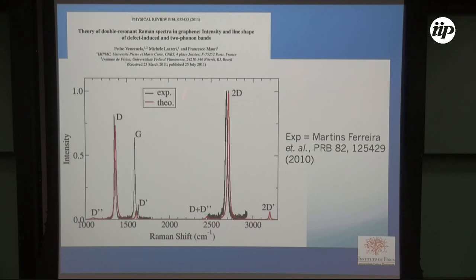Look at these peaks. Those three peaks, they are due to two phonons, okay? And there is not one single adjustment parameter in this calculation. The only thing that I adjust is the intensity of the 2D peak experimentally and theoretically. And then we have a very, very good agreement, okay? There is a disagreement in frequency. This is due to the inaccuracy in the phonon calculation. This disagreement is of the order of 40 centimeters to the minus one, which corresponds to milli electron volts. So it's very difficult to have a phonon calculation with accuracy better than the order of milli electron volts.